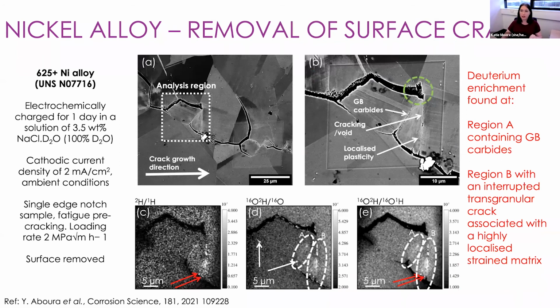Now, as I said, we get some surface cracking, and we were not really looking at the actual crack tip in that previous example. So Yasser wanted to try and find the real crack tip in the middle of the sample. Now the surface has been ground away to try and make sure we remove all of those surface cracks, and we're really looking at the main crack running through the sample. Unfortunately, we didn't manage to find the real crack tip, but this is an area that proved to be quite interesting here.